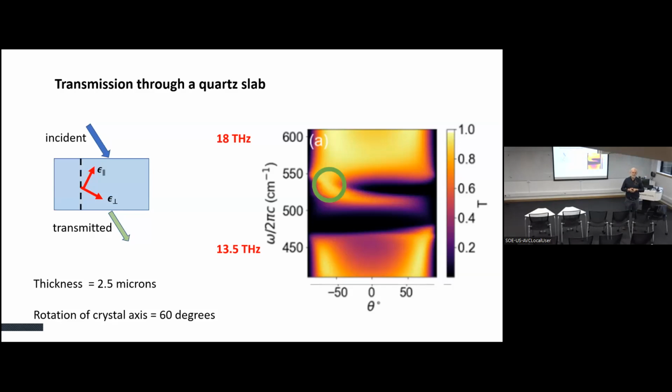The answer is, did we play around? Not very much. We made the thickness different. The same kinds of things happen, and it wasn't clear exactly what we would aim for as an optimal result. The other thing is, you don't want it too thick because you start absorbing more. In any electromagnetic setting, you want as much transmission, as big a difference, I should say, as possible. So we stayed with relatively thin films, but clearly there are a lot of additional steps you could do if you had a particular application in mind.